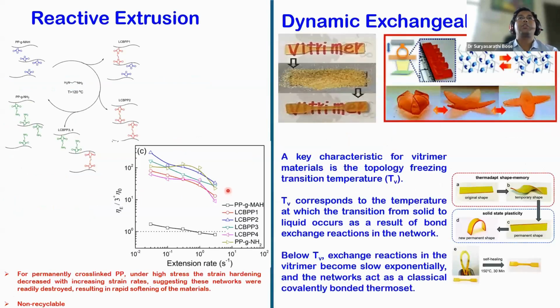So you might ask me, what is the difference between a reactive extrusion and CANs? Yes, there is a whole lot of difference. In the case of reactive extrusion, which many of you might follow, you have maleated polypropylene. As you can see, there are maleic anhydride groups. You bring in molecules that can permanently form covalent bonds, which means if I bring an amine closer to this anhydride at higher temperatures, they quickly bond.